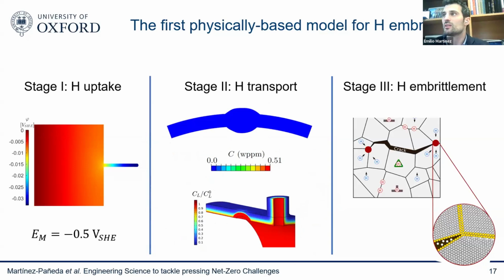And then when you do that, when you see something like you see here, you can see, for example, distribution of hydrogen within this component. This is a pipeline. You can see we're increasing the pressure inside of the pipeline, so the hydrogen concentration increases, and the hydrogen diffuses within the pipeline from the maximum on the inside to the minimum on the outside. And here you can see a different component, it has a defect, and so on and so forth. So once you have the PDEs that are solving your problem, you did the experiment, you have the material properties that drive those PDEs, you implement this into a finite element problem, and you can quantify what is the distribution of hydrogen within your component.